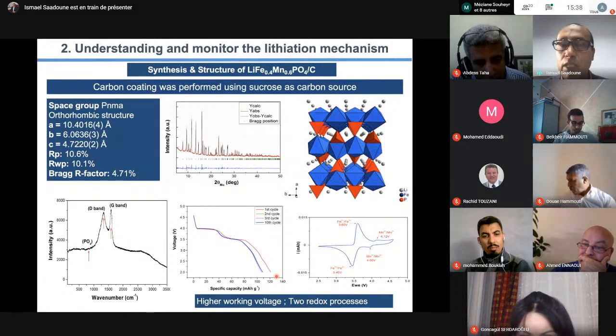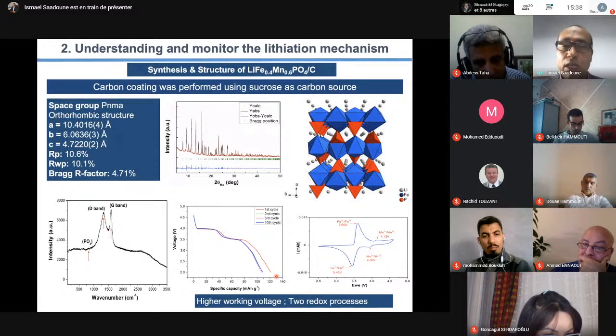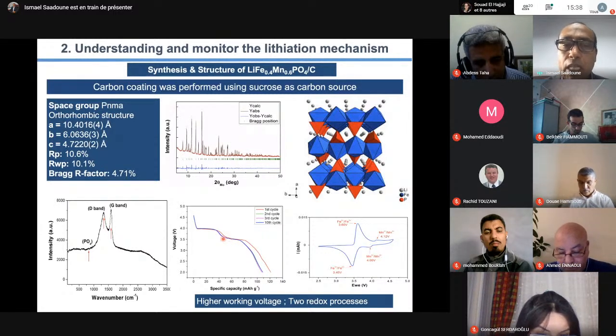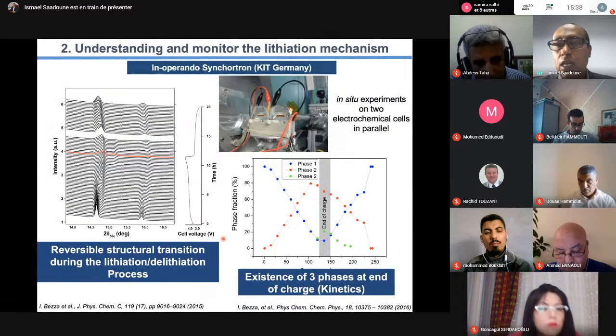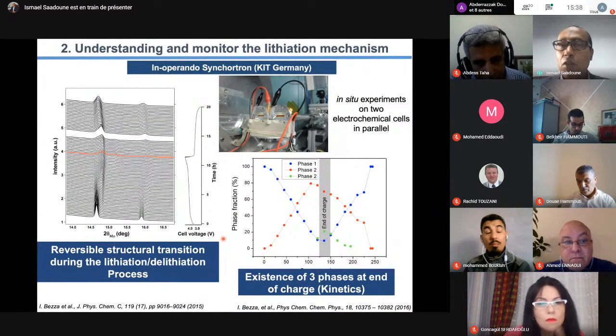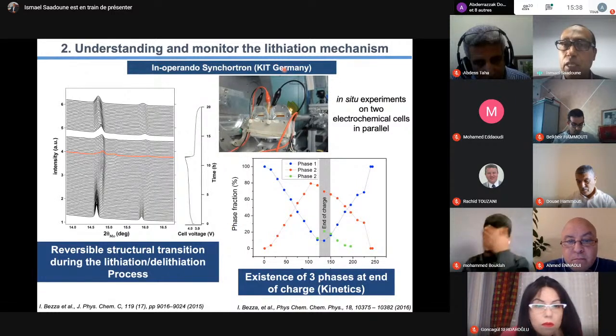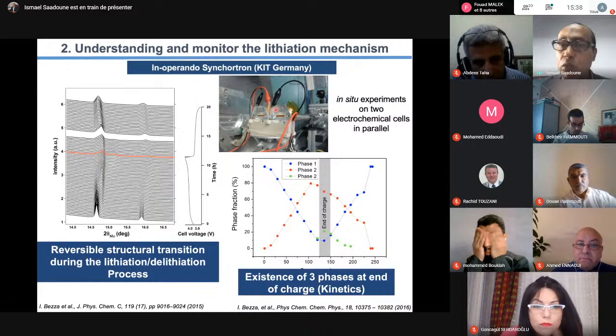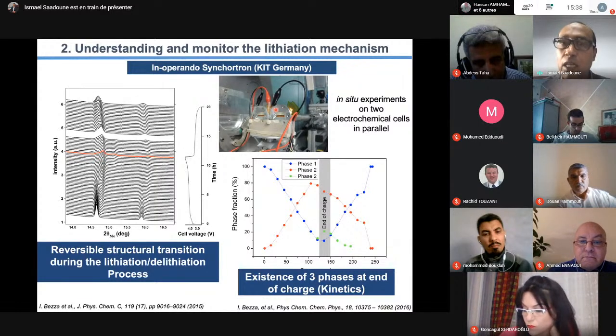And to understand what happened, we use in-situ XRD to follow up what happened during cycling, at each point of the charge and discharge process. This was the aim of our collaboration with KIT Germany, within some win-win collaboration. We prepare our material in Morocco and we use the facilities there. And you see here they have some special cell, two cells simultaneously, to check the reproducibility during charge and discharge.